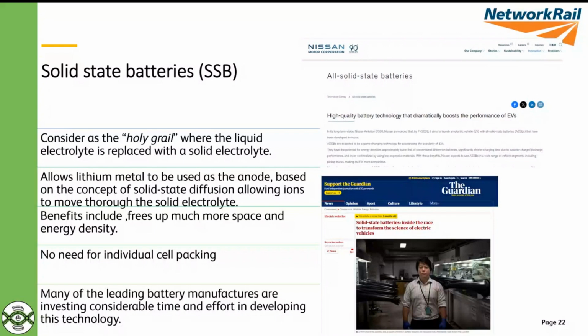However, that by itself doesn't really do anything. It actually makes the performance of the battery worse, because the solid electrolyte is about 5 times denser than the liquid electrolyte. Where you start to get the benefit is in moving towards using lithium metal as the anode, because lithium metal has about 10 times the specific capacity of graphite, so you get a significant increase. And also the size of the battery can now vary, because to hold 1 atom of a lithium ion, you need 6 carbon atoms.